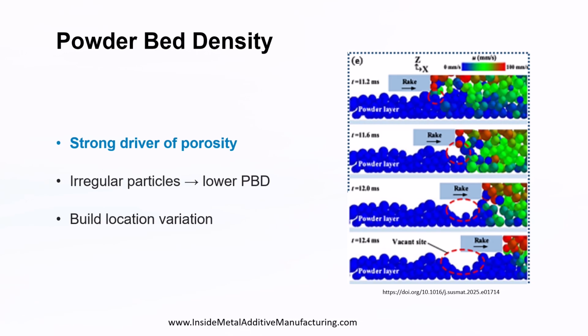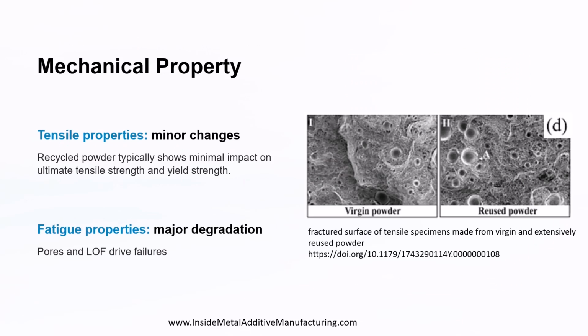Recycled powders often reduce PBD because irregular particles don't pack efficiently. Large spatters interfere with smooth spreading, and the recoater can create local segregation across the bed. Lower PBD means more porosity, and more porosity means weaker fatigue performance. Now let's see how all of these powder level changes translate into actual part performance.